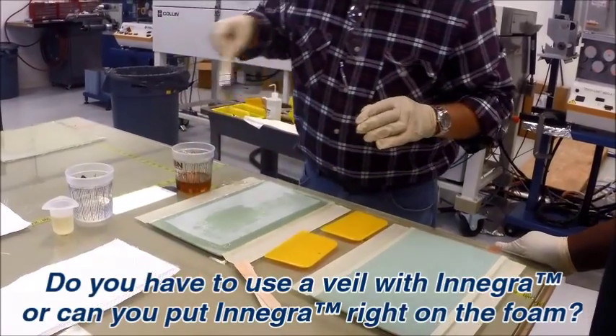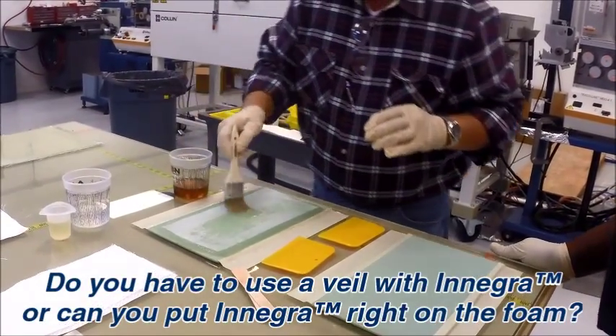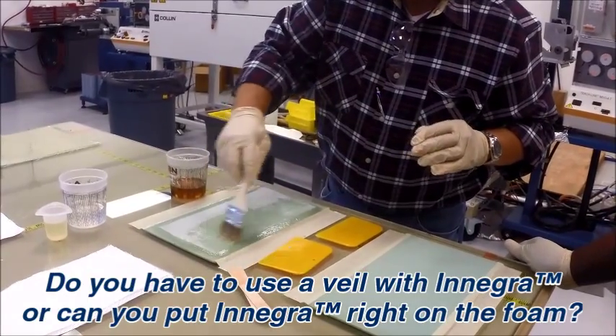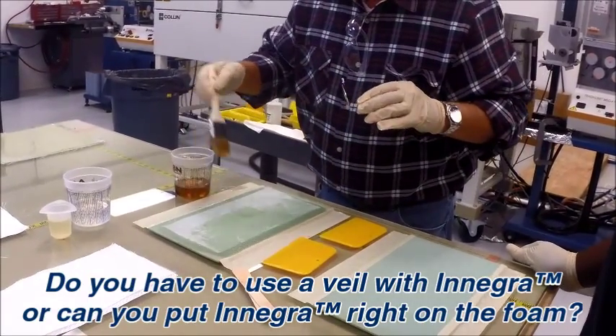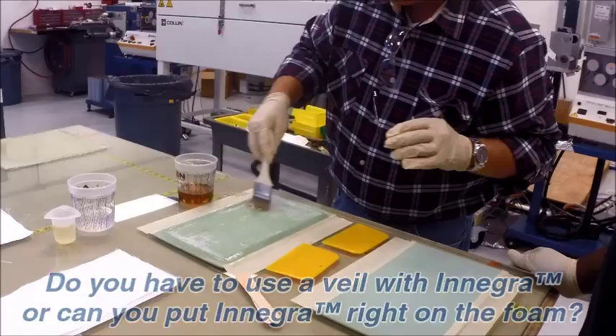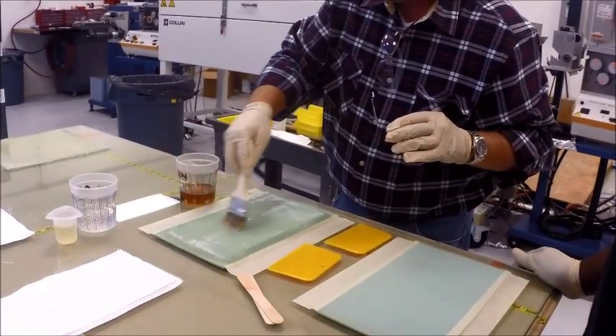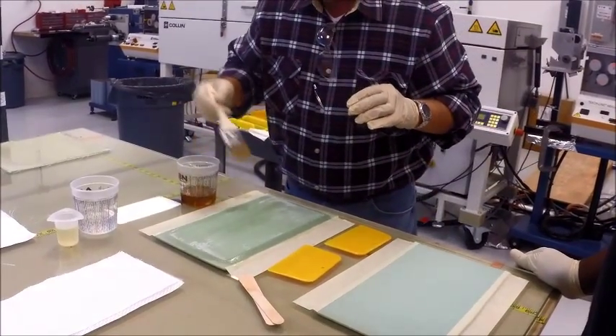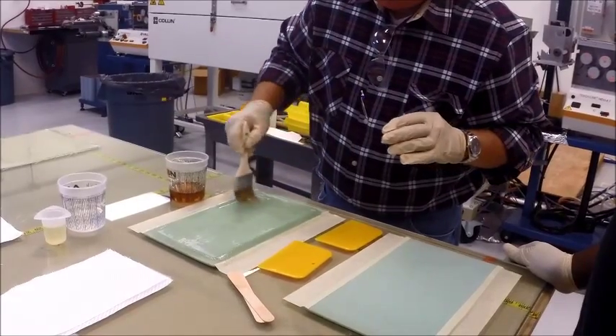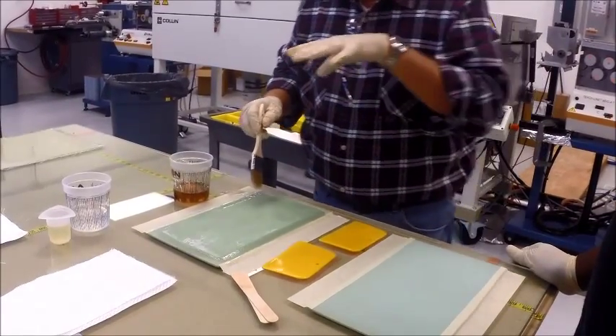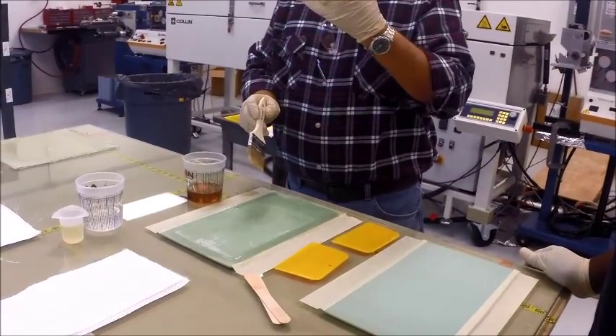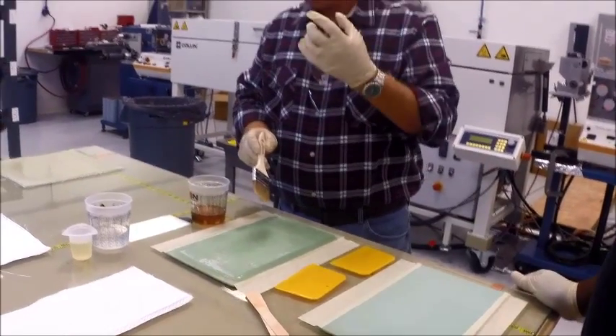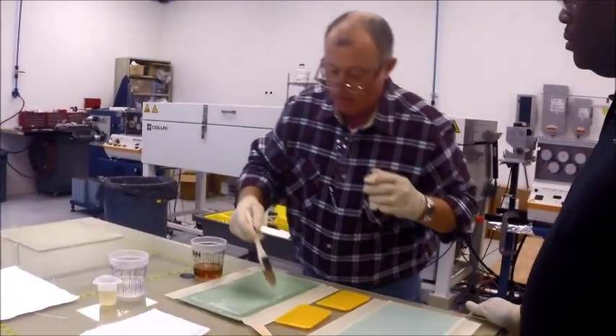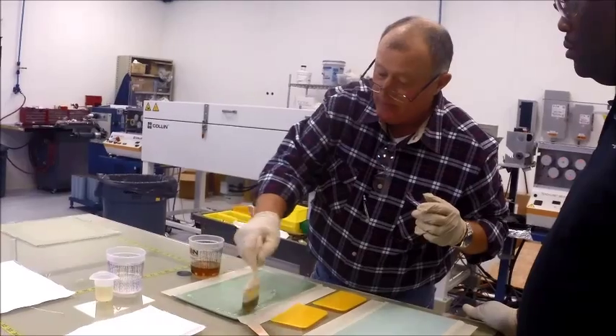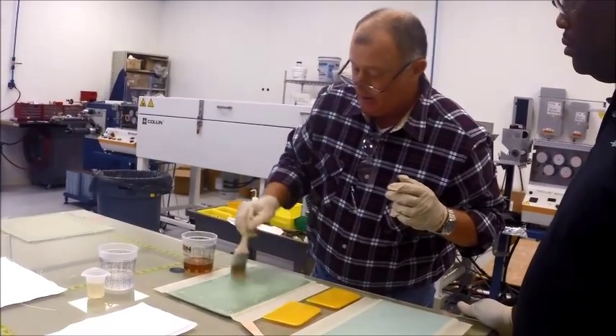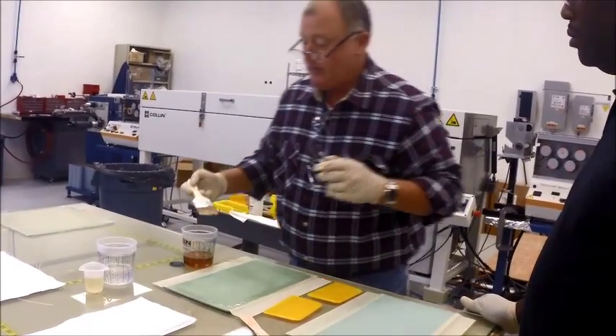Do you have to use a veil when using Innegra? Can you put Innegra right on the foam? I feel very strongly that we need to have a very light veil against the foam to get a good encapsulation of the Innegra and to prevent the foam from drawing the resin out of the laminate that you put down because of the hydrophobic nature of the Innegra. So, as you can see, sounds very nice.